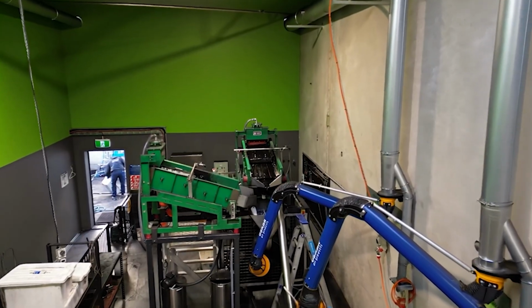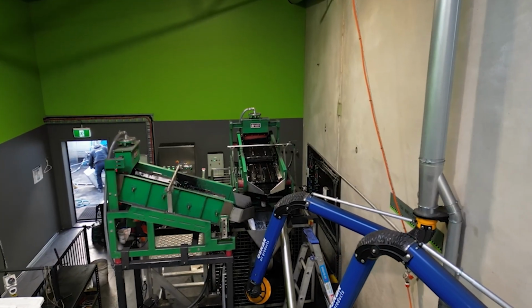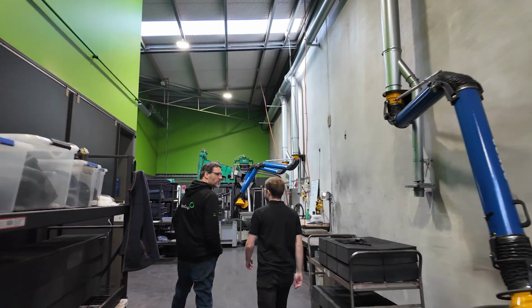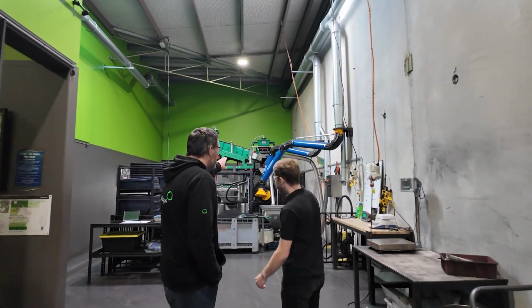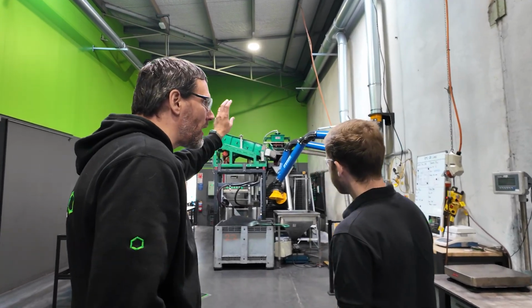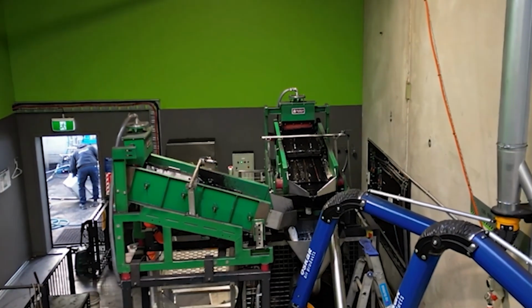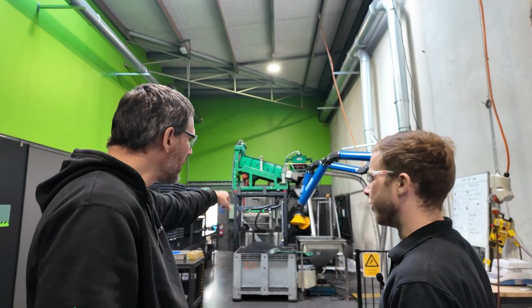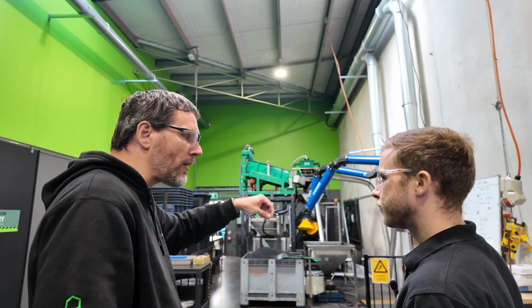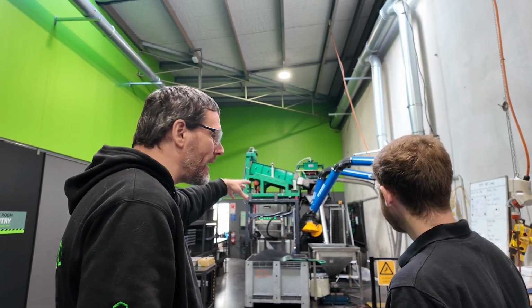Once the biochar is on site, the first real processing step is to grind it down to the right particle size and distribution. This is the, well, it used to be a rod mill, now it's a ball mill. And so that's how we process the biochar. So the charcoal then gets ground down to the size that we want and screened and filtered.